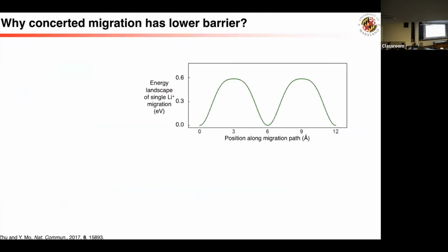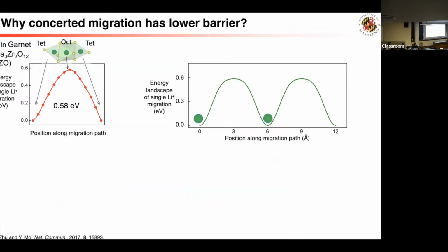So basically, you have this energy profile, for example, given by the equilibrium site of lithium. Normally, you would expect lithium just sitting at the bottom here. And if you closely examine this super-ionic conductor, you will find, and this is from DFT, that on this site it's actually sitting on the top of the energy profile. So in this material, you will also have lithium ions there.